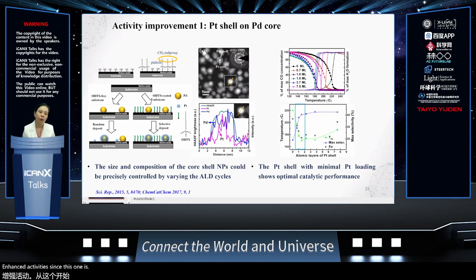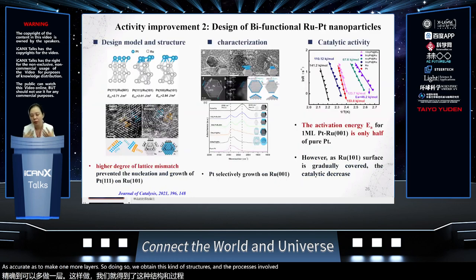In this one, we utilize self-assembled monolayers. We just run it very quickly, just a few seconds, and it will leave a few pinholes. Through the pinholes, we will be able to form these kind of core shell structures. If you don't do these pinholes, we actually get some newly nucleated small nuclei. So you not only obtain the core shell structure, but also obtain a new second type of material. When you run ALD, the core shell material you obtain is as accurate as one monolayer. Doing so, we obtain this kind of structure, and the process enables good activities with a minimum platinum amount. So that's showing you how we utilize the template method.